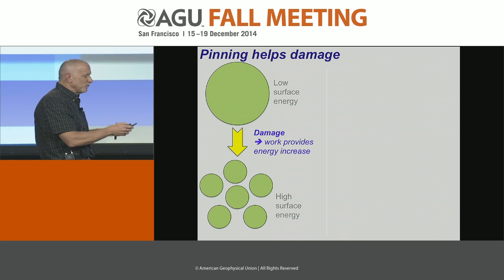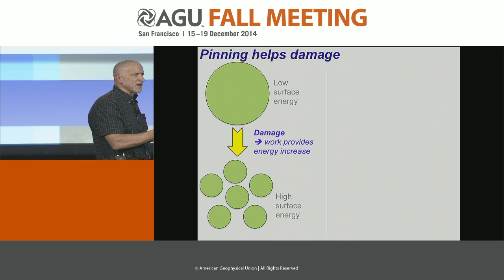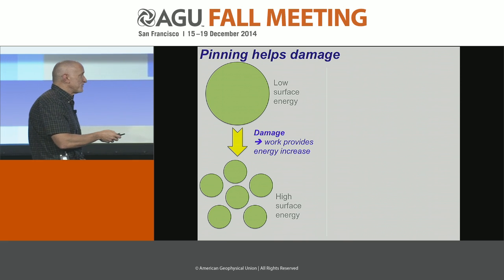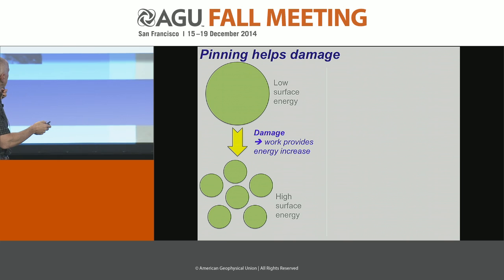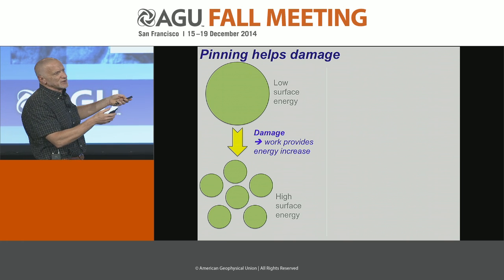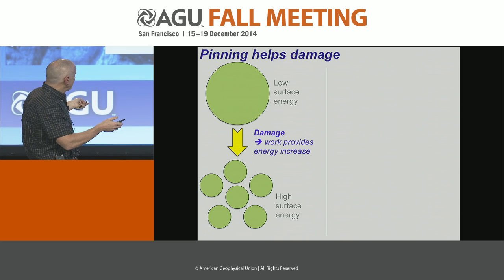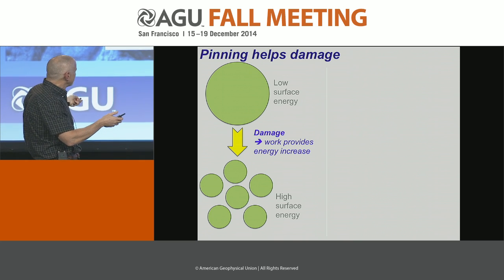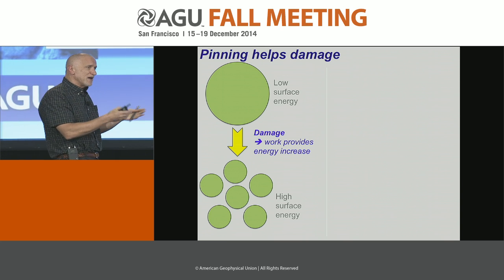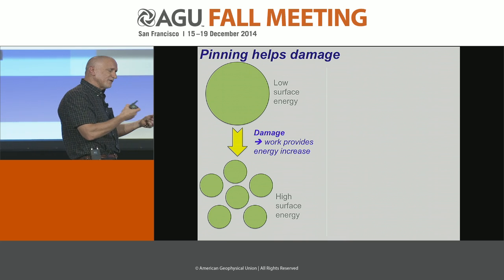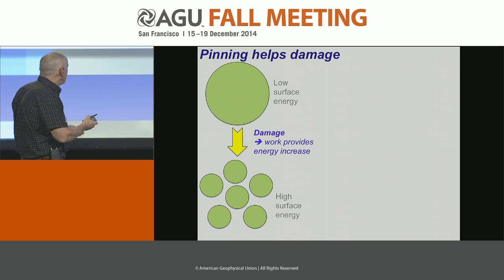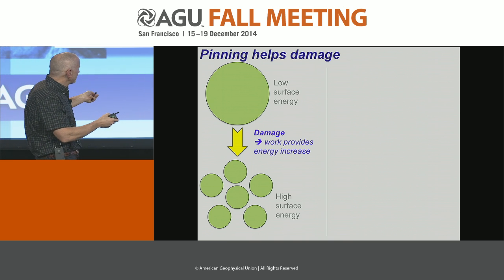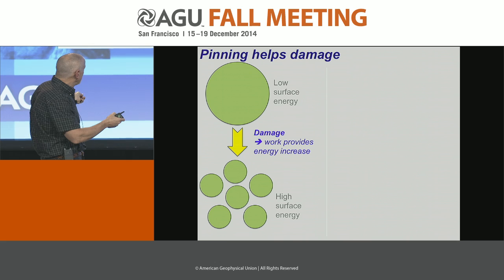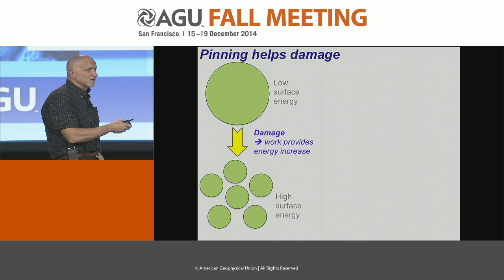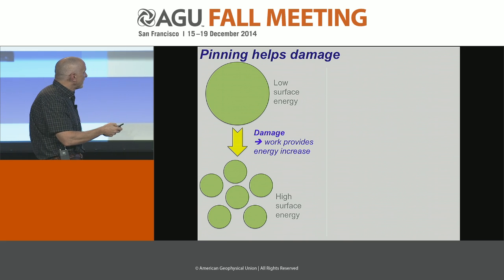What do I mean by damage? When I say damage in the broad energetic sense, just in terms of transferring energy, that's really what damage theories mean. If I'm going from a big grain and breaking it into smaller grains, I have to create more surface energy, and to get that more surface energy associated with all these extra surfaces, I need some energy, and that is only going to come from the work that I do to grind it down. So it's almost like Griffith's crack theory. I need to have some work to create new surfaces. So the damage comes from the deformational work, and that's what we mean by damage.